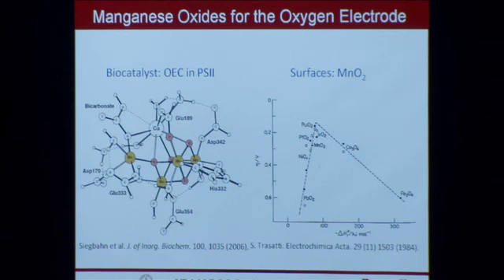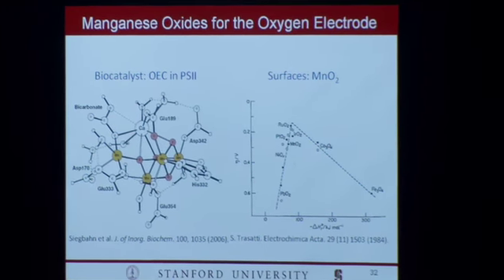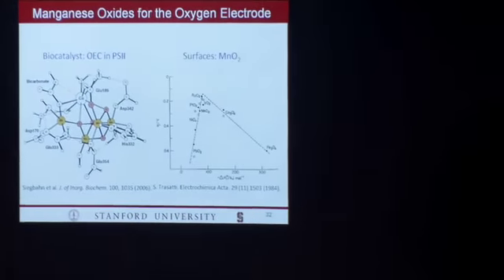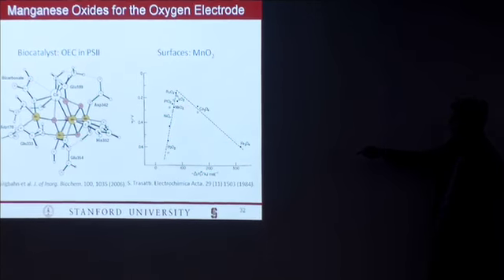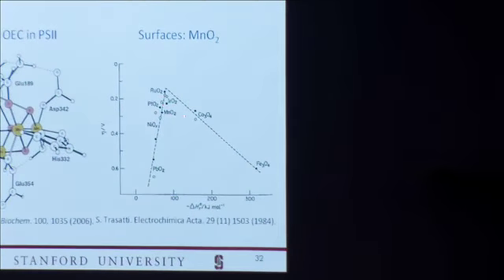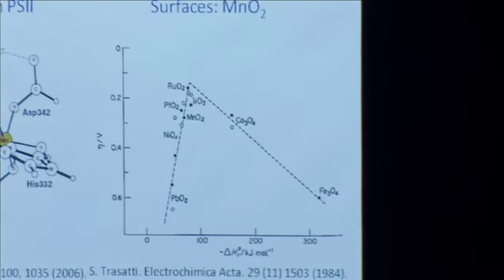And so we asked ourselves the question, well, perhaps there's a way to emulate what the Oxygen Evolving Complex does, but in a hard material, in something that's more robust and more commercially applicable than an enzyme or a protein that you would end up putting onto a surface. So we looked into literature for manganese oxides, and this is a volcano plot that shows the activity for oxygen evolution reaction, water oxidation. You can see here again, ruthenium and iridium are the best. Platinum's very good, not quite as good as these two, though. And then there's manganese oxide, which is not such a bad catalyst as well.